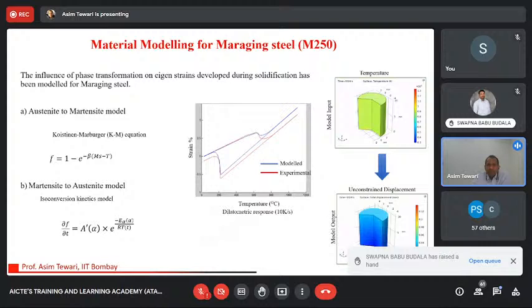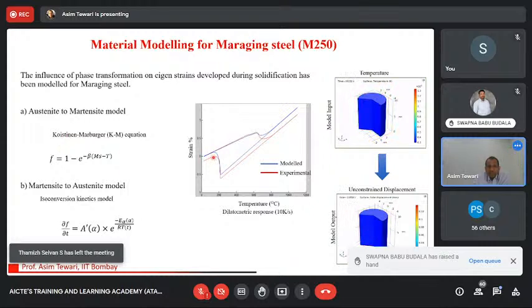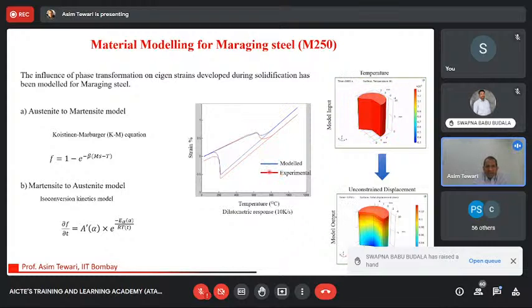So this is what is happening in terms of phase transformation. You have a materials model, especially in this case for maraging steel, and this maraging steel is going through austenite to martensite phase transformation, which is following this expression. And what you see is that this is the model and this is the experiment. Blue is the model, red is the experiment. And as the temperature is changing, the material expands, but then suddenly goes through a reduction and then again goes to expansion. Why is this happening?